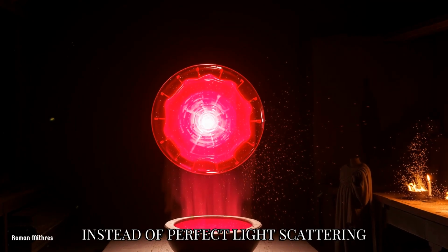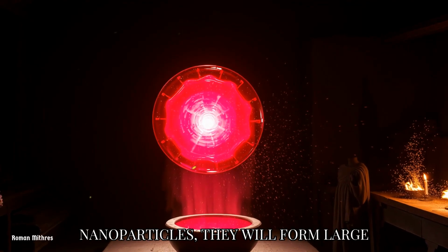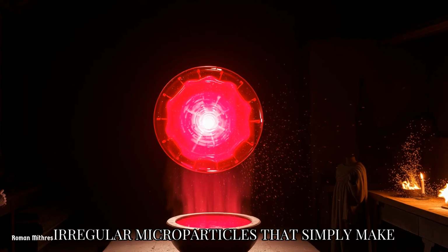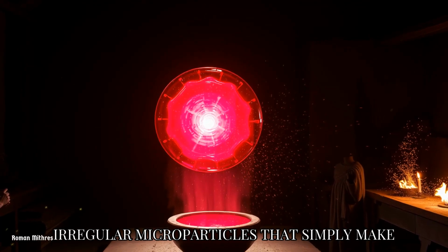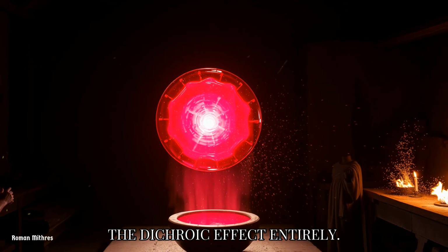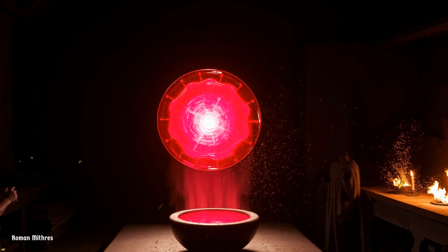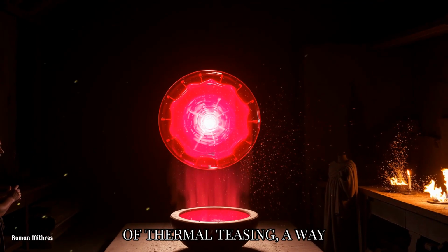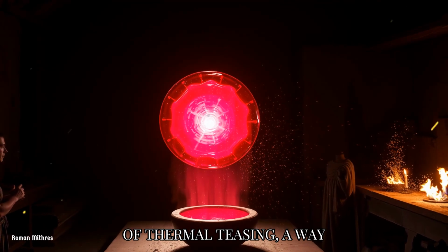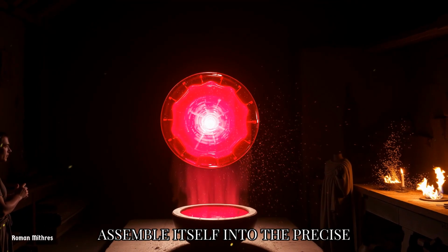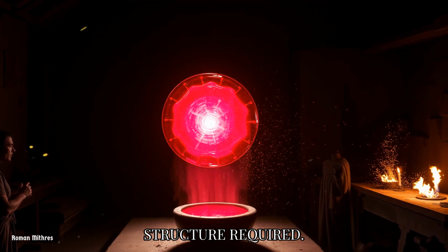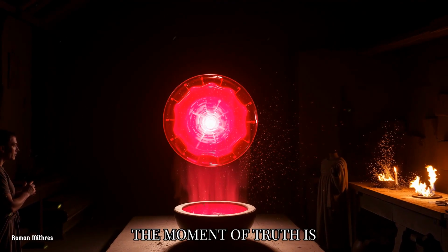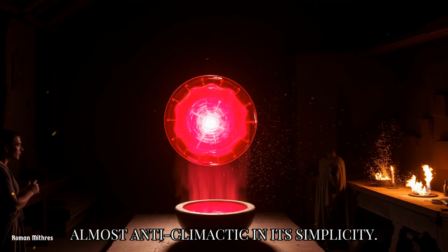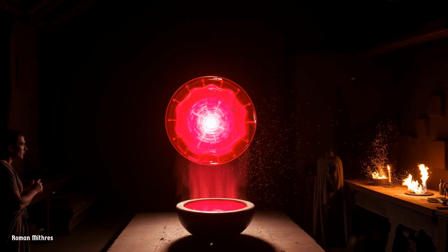Instead of perfect, light-scattering nanoparticles, they will form large, irregular microparticles that simply make the glass opaque and destroy the dichroic effect entirely. The strike is a process of thermal teasing, a way of convincing the material to assemble itself into the precise structure required.